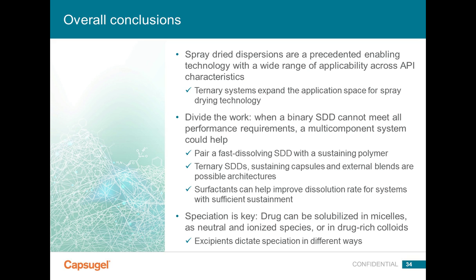Surfactants are able to help improve the dissolution rate for systems with sufficient sustainment. And the key in our design is the speciation, so what kind of drug species are formed during a dissolution test. The drug can be solubilized in micelles as neutral or ionized species, or in drug-rich colloids, and different excipients are going to help you dictate that speciation in different ways that you can help target what you need to make your formulation succeed.